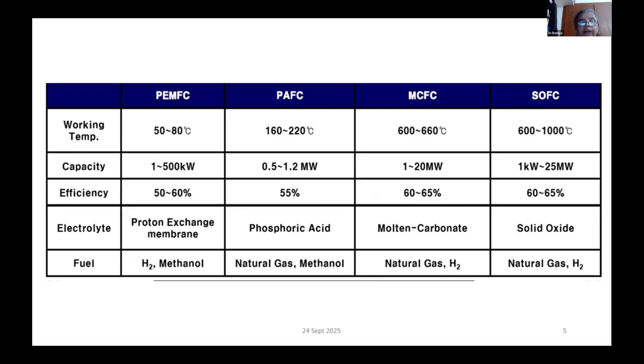Like I said, we are doing polymer electrolyte membrane based fuel cell. You have other types of fuel cell also: phosphoric acid, molten carbonate, or solid oxide. It all depends on what your working temperature is and what your electrolyte is. If you are looking at low temperature fuel cells, alkaline or polymer electrolyte membrane based fuel cells are useful because these operate in the temperature range of 50 to 80 degrees centigrade, and they can be easily started. They are amenable for low temperature startup, and they are quite well developed, in the sense they are commercialized also. There are buses running with polymer electrolyte membrane fuel cell, and they have a good efficiency, about 50%, and you can have hydrogen or methanol as a fuel.